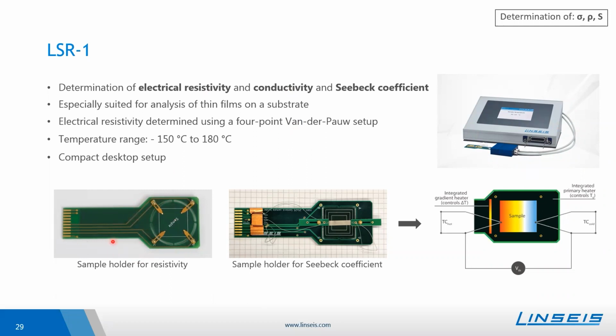We use here such sample boards where you place the sample on top and contact the sample with these 4 needles. The sample holder for the Seebeck coefficient looks a little different, where you put the sample on top and there are some thermocouple wires touching the sample to be able to find out the Seebeck coefficient. So these are 2 instruments for the electrical conductivity determination, which might be of interest.